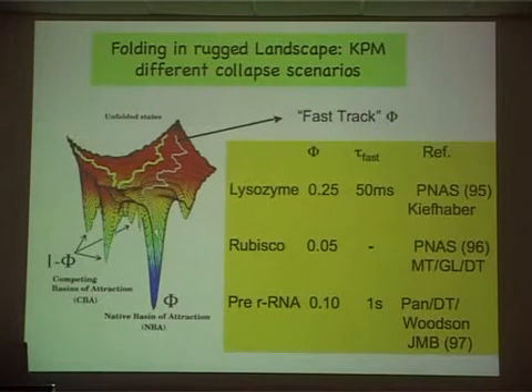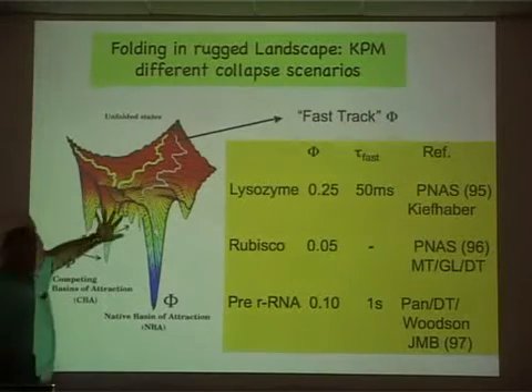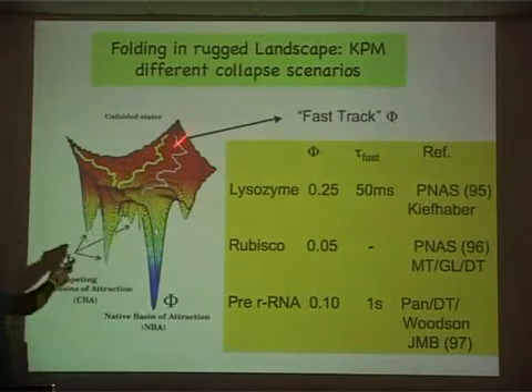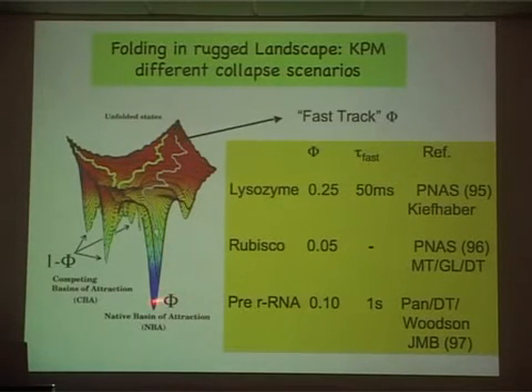So what happens if you have a more complicated rugged energy landscape? So supposing you didn't have all these other competing basins of attraction, then any molecule that starts from anywhere in the landscape would in fact go with sufficiently large probability to the native basin of attraction. That is not the case for these sorts of examples that I show here, and there are various other proteins, lysozyme, rubisco, the most abundant protein on Earth because it's in plants, and this is RNA. It turns out that, and these are all experimental numbers, and there's a huge amount of literature starting from '95 to now that describe this so-called kinetic partitioning mechanism, in which we imagine some fraction of molecules, in fact, traverse this landscape very directly to the native basin of attraction, whereas many other molecules get trapped in many competing basins of attraction, and thermal fluctuations will have to assist them in overcoming the barrier on a longer time scale to go to the native state.